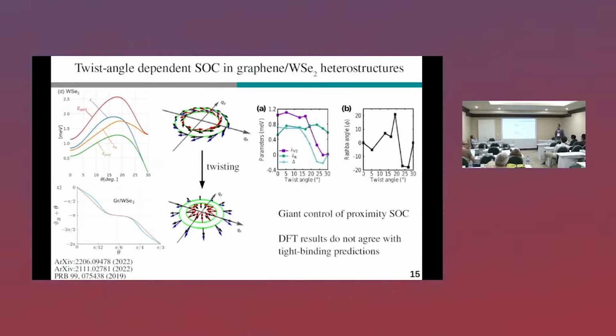Now if you do actual DFT calculations on large supercells, you will find that the proximity spin-orbit coupling can indeed be heavily tuned, but the results do not completely agree with what the tight binding picture says, because, for example, this valley-Zeeman spin-orbit coupling has here more or less a plateau and then drops to 0 at 30 degrees.